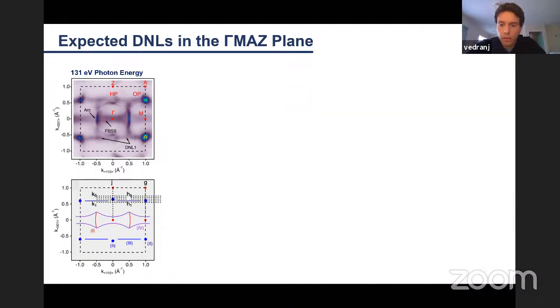And now we return to our main Fermi surface schematic, and we could take a closer look at the band dispersion of direct nodal line 1. Let me just be mindful of the time that I'm taking. Actually, I may not have time to go through this slide, but essentially it does the analogous view of the band dispersion of the direct nodal line 1 along the gamma z direction. And it was actually depicted in these ARPES images, but essentially it's proving what the DFT calculations show.